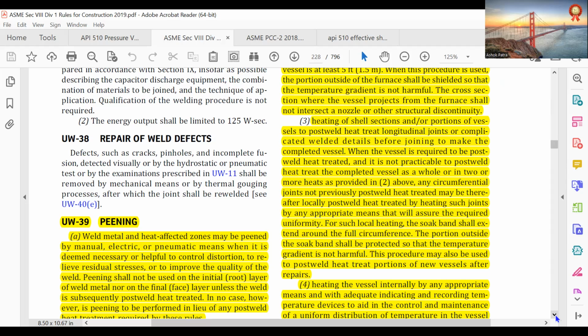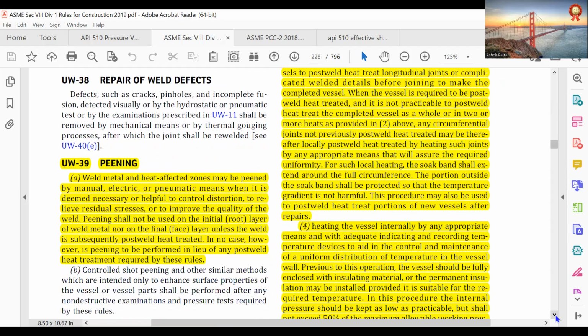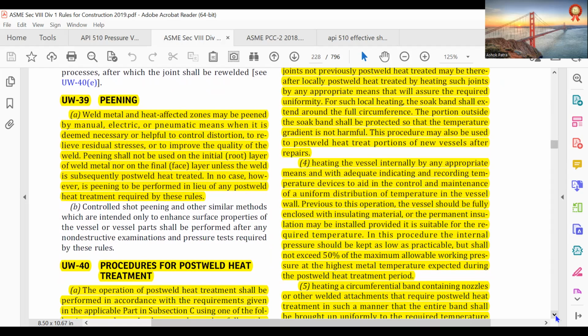Heating the vessel internally by any appropriate means and with adequate indicating and recording temperature devices to aid in the control and maintenance of a uniform distribution of temperature in the vessel wall. Previous to this operation, the vessel should be fully enclosed. The insulating material or the permanent insulation may be installed provided it is suitable for the required temperature. In this procedure, the internal pressure should be kept as low as practicable, but shall not exceed 50% of the maximum allowable working pressure at the highest metal temperature expected during the post-weld heat treatment period.